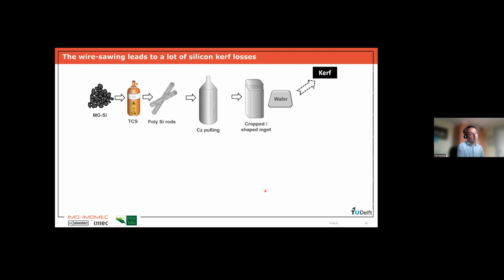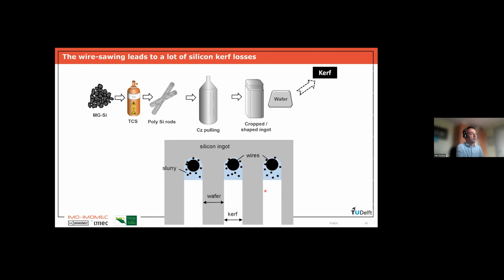Now, the problem with this process is that it leads to a lot of silicon kerf losses. So we lose part of the ingot. Why is that? These wires have a certain dimension. Typically, they are around 80 to 100 micrometer in width. We cannot make them too thin because then the wire can easily break, which is not what you want to have. And so these wires are cutting through the silicon, but everywhere where they cut, basically they pulverize the